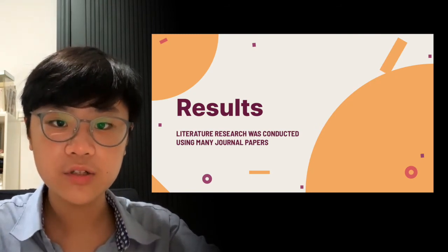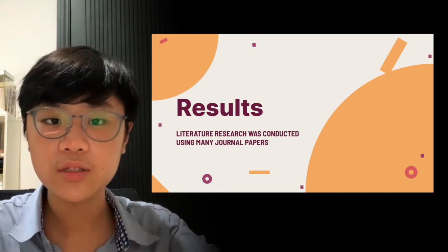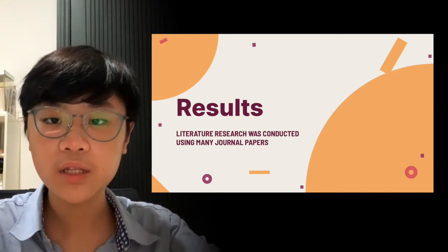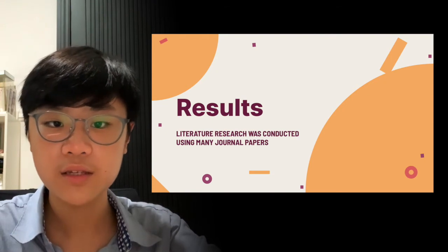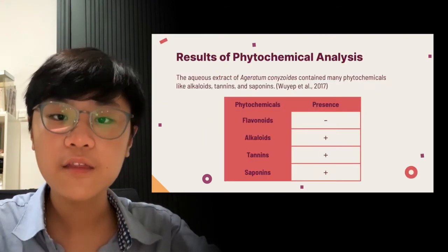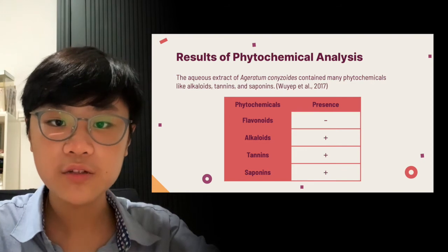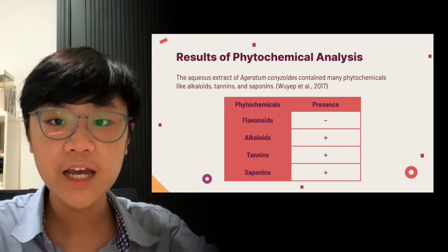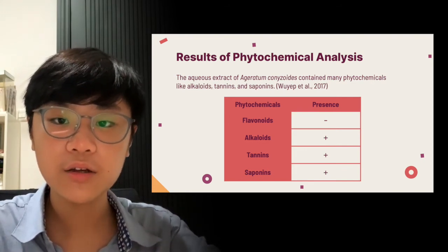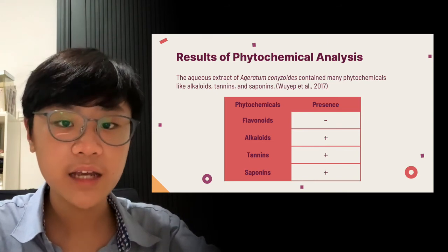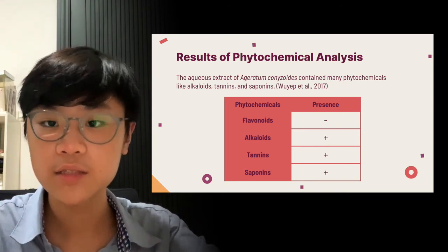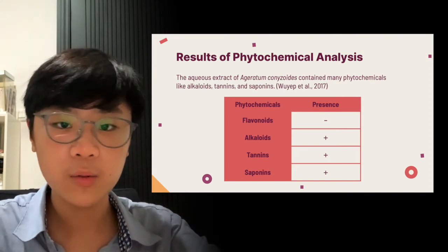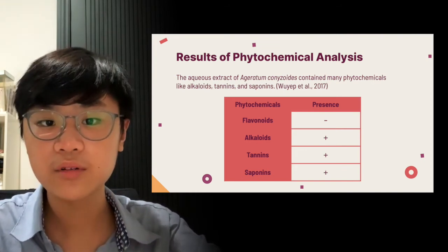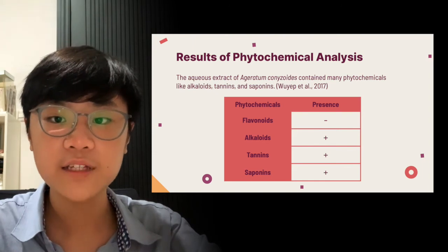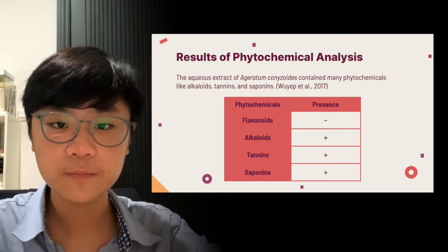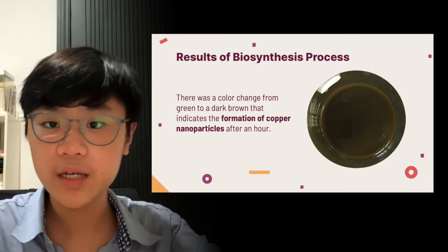Literature research was conducted using many journal papers to predict and show the results of the copper nanoparticles that were formed by biosynthesis. First, the phytochemical analysis showed that the aqueous extract of Cu-Ageratum conyzoides leaf extract did contain phytochemicals like alkaloids, tannins, and saponins that have an active function in the biosynthesis process. Only flavonoids were not present, and even so, the other chemicals indicate that the extract can effectively synthesize copper nanoparticles.